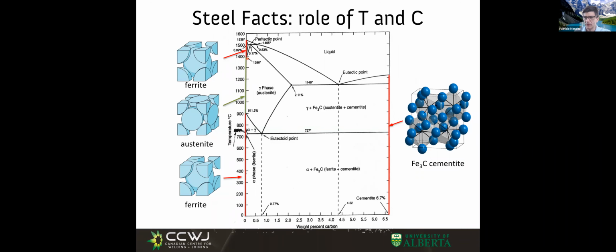But if I add carbon - carbon is what's called an austenite stabilizer - look at this: the temperature range at which I'd have austenite can be lower and can be higher. So austenite will exist even colder than before, because carbon stabilizes it, and hotter than before too. So all this area indicates a mixture of iron with carbon in solution, and that's all I have.